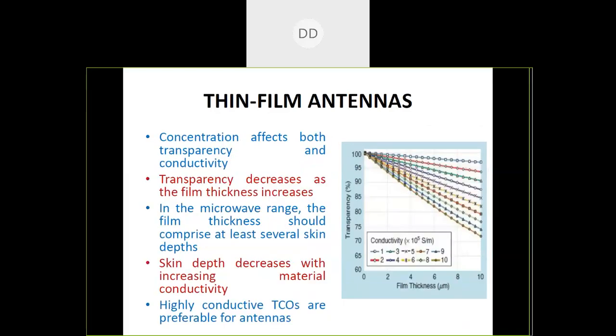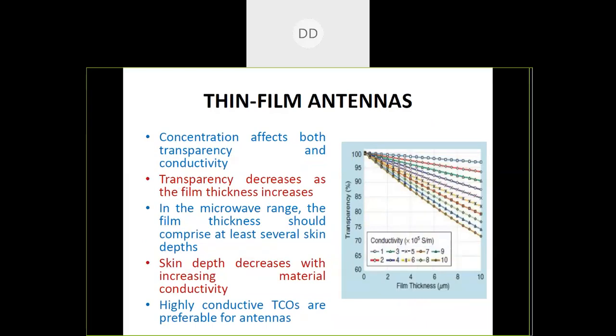If we go through this particular diagram, here we can see the transparency of ITO and gallium doped zinc oxide film versus the film thickness. This diagram shows the comparison between the doped zinc oxide and indium tin oxide, ITO, transparency versus film thickness. We can see the thickness dependence of the optical transparency. For ITO and this gallium doped zinc oxide, it depends upon the carrier concentration values also. Carrier concentration values have been shown as 1, 2, 3, 4. Different colors show these different carrier concentration values.